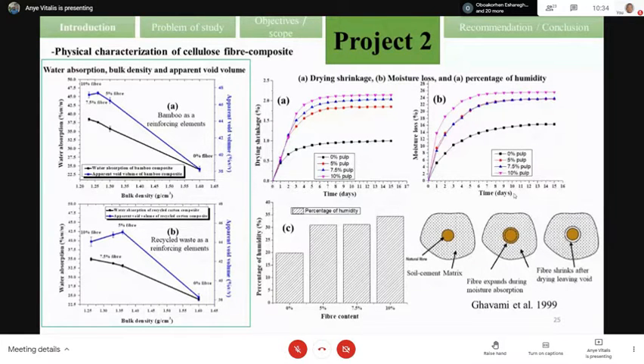Also, by studying the virgin fiber and recycled fiber, we realize that the recycled fiber was giving a low water absorption, a low porosity, and a high density compared to virgin fiber. So by studying the density of the individual fiber, we realize that recycled fiber has a high density compared to virgin fiber. Also, this can be due to the fact that applying the recycling process behaves like a treatment which can have an impact on the modification of the water absorption and also the dimensional stabilization of our recycled fiber.